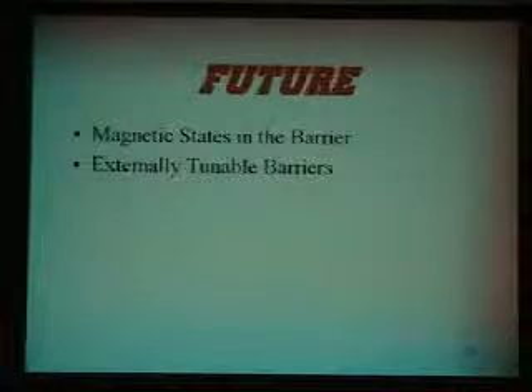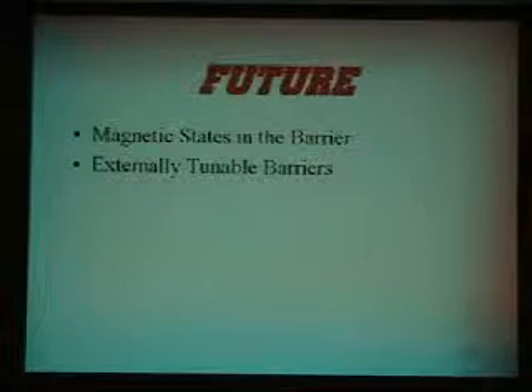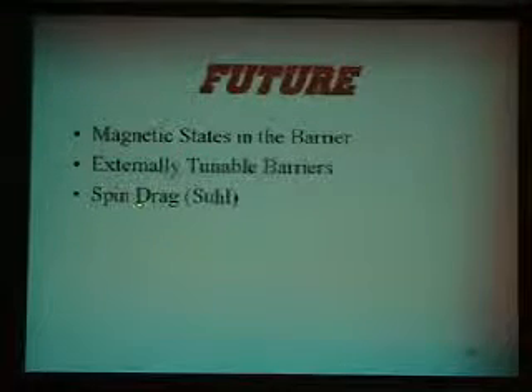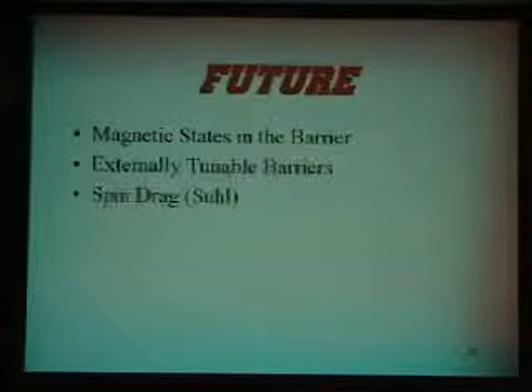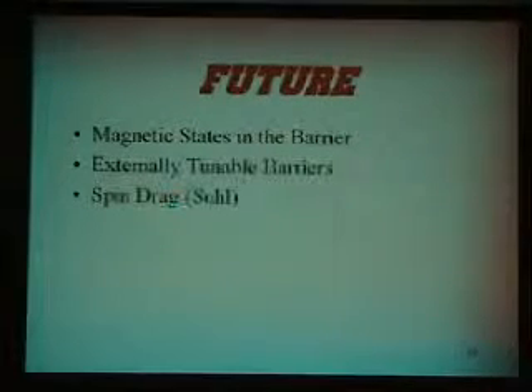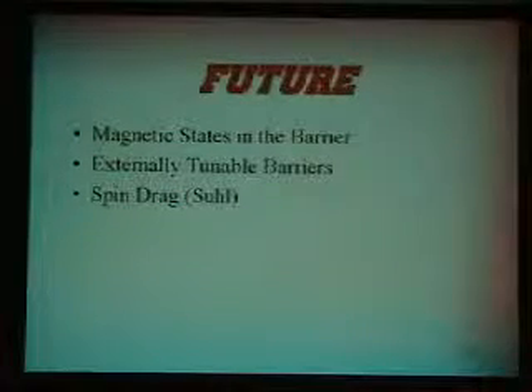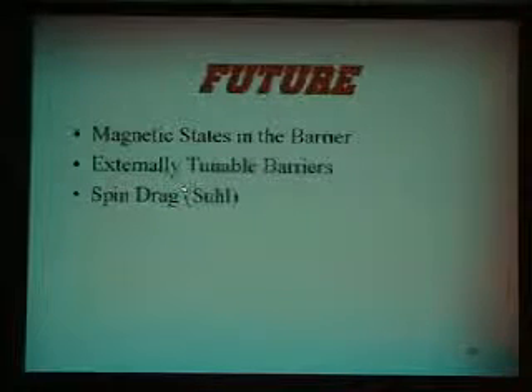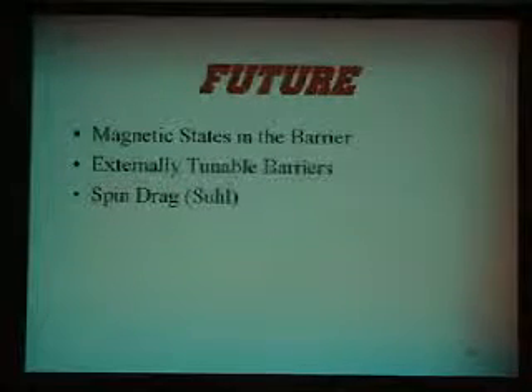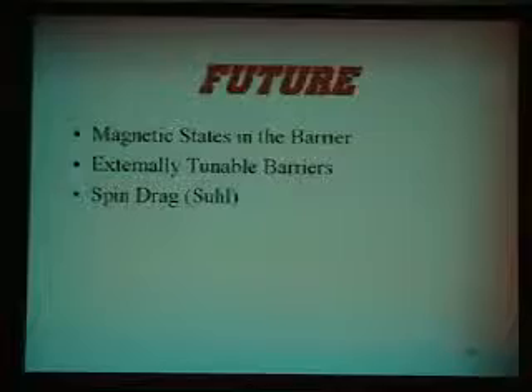This was explored in the superconducting case. I don't think it's been explored in the magnetic case. Harry Suhl and I have been talking about this. Harry came up with the idea of something called spin drag. This has nothing to do with the ladies in San Francisco. It has to do with the fact that if you attach an electrode on one of the layers and put a current in the other layer, you may have a spin polarized drag. The spins on one layer may drag the spins on the other layer.